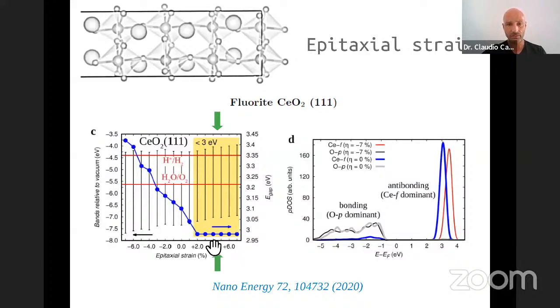However, as you increase this tensile stress, or strain, on this material, you come to a region from 2% on in which your band gap is reduced down to 3 electron volts, which is good for absorption of sunlight, right? And at the same time, the band alignments tend to be positioned at a more optimal value in order to drive this